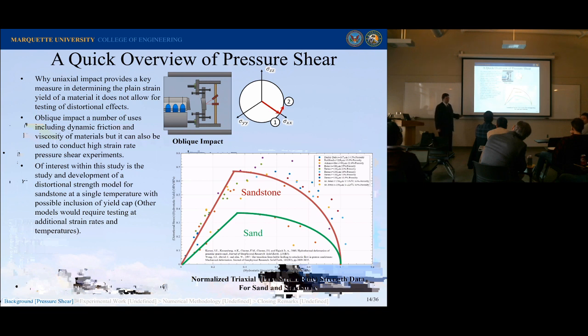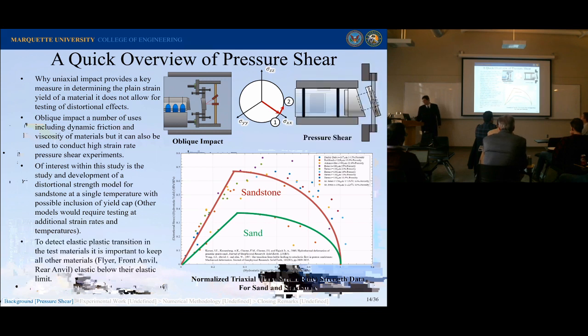So you can see this data that already exists. This is at low strain rate. So we would anticipate that we might have a larger curve right here when we go at higher strain rate. But if we look at porosity, you can definitely see that porosity is having an effect on strength. I've normalized it here, so if I actually were to take off the non-dimensionalization, you can see that the sandstone goes and has that same curve as we saw in the previous slide, where it's getting much stronger for lower porosity.